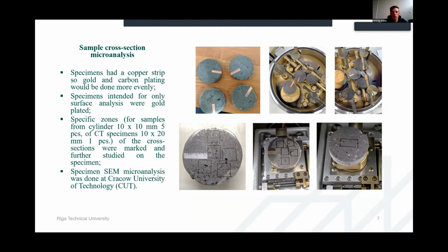The samples had a copper strip added to them, and after the plating procedure, the specific zones, as you can see in the bottom part of the images, were put onto the specimens so that it would be much easier to track inside the microscope where the specific areas are that images are to be taken of. For the samples taken from the cylindrical specimens, there were 5 specific zones added. Each zone was 10 by 10 millimeters. And as for the tension tested specimens, they had one zone, 10 by 20 millimeters, and it was placed at the base of the notch for the CT specimens.